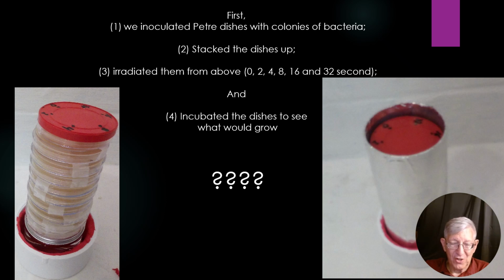individual petri dishes. All of them were inoculated with the same stuff at the same time, within minutes of one another. And then they were stacked up, as you see here, and probably about 18 hours later or less, they were irradiated. Now, this was our first experiment, and we were kind of sloppy. We weren't collecting all the data we probably should have.